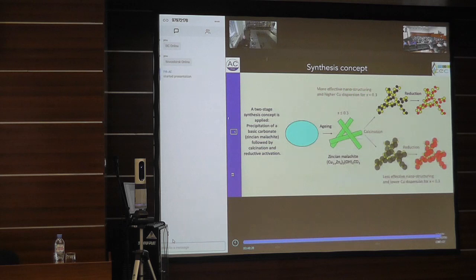What's the problem? The problem lies, of course, in the fact that you have to get exactly the right relative size of the two particles. It's very easily understandable if you get this wrong, that either you have too small zinc oxide and too large copper particles, or you have the other way around, and then you get a phase separation, and it's only a good catalyst if the zinc oxide particles and the copper particles have exactly the same size. That's not so easy if you think that a typical synthesis of such a catalyst is 25 tons. So you have a problem, you cannot use any auxiliary reagents and no templating molecules, and so that's all excluded because otherwise that would not be economical anymore.